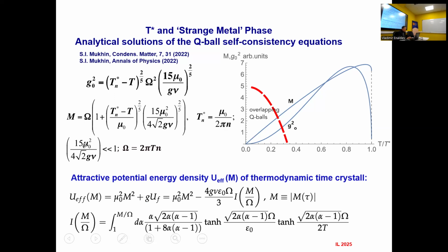So now, in this limit, you remember that mu sub 0 squared is actually the mass of the M field. So this is the inverse correlation length of the charge fluctuation or spin fluctuation squared. G is a coupling constant between phonons or spin waves and fermions. Nu is the density of states at the nesting point, at the Fermi surface, at the Fermi level. And when this is much less than 1, we call this strong coupling.